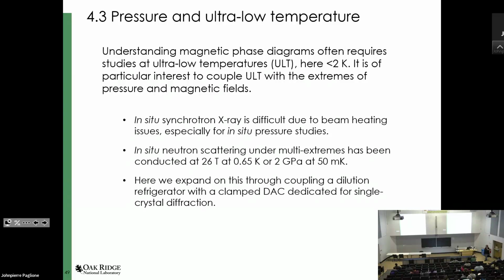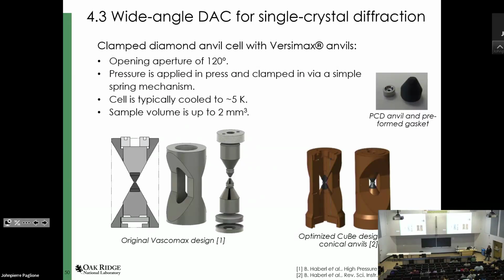With neutron scattering, you have less flux, so you have less beam heating. Neutron scattering has been very good at ultra-low temperatures, and at coupling diverse extreme environments like magnets or clamp cells with dilution refrigerators, for example. Here we did not use our new megabar diamond cell. We used a previous iteration made from copper beryllium. This cell was developed for inelastic neutron scattering on the VISION spectrometer, but was mainly used for single crystal diffraction across the instrument suite, at various single crystal diffractometers at SNS and HFIR.